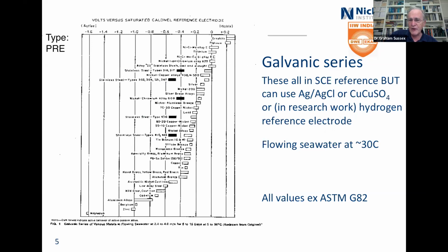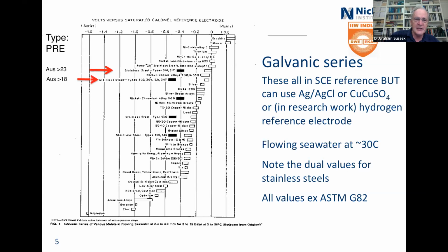This chart is for flowing seawater at about 30 degrees C, and note, there's little black bits on, say, 316, or a white bit open. And that's basically the 2 states that it can occur in. If it's white, that's where you want it to be. It's not corroding. If it does break down and start corroding, then the potential pulls back down there. And that's the same thing that's happened for 316, for austenitics with 18, so a 304, down to a ferritic at about 16, or a martensitic at 14. All of the stainless steels have this dual arrangement, but because you don't want your stainless steel to corrode, then it should be in the zone where you've actually got the open square there.